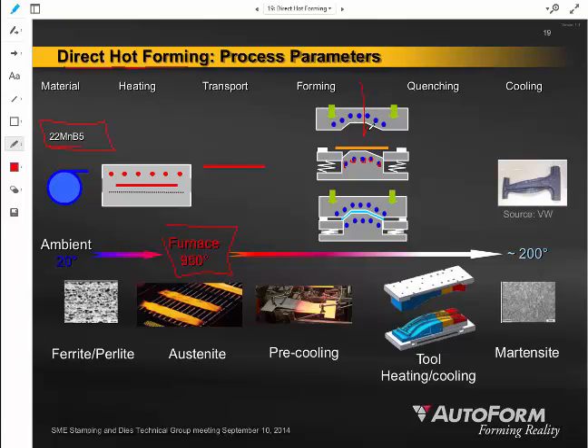And that way, when we close the die on the material, the material is getting deformed and the material is quenching in the meantime. So normally what will happen is you put the blank in, it takes 1 second, maybe 1.5 seconds to close the die, and then the die is going to stay closed, maybe dwelling at the bottom for, I don't know, 3, 5, maybe even 6 seconds, cooling and quenching at the bottom of the stroke. And as that's happening, the material's microstructure is going from this 950 degree austenitic microstructure possibly towards martensite or bainite or ferrite microstructure, and achieving certain yield strength and tensile strength characteristics.